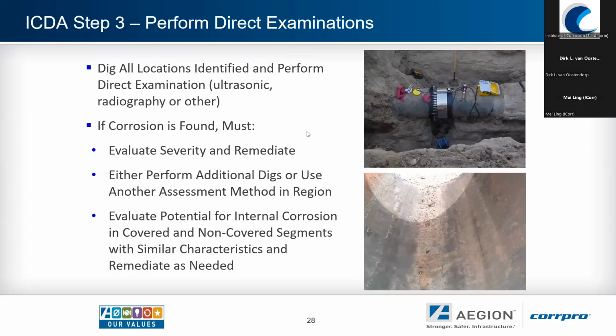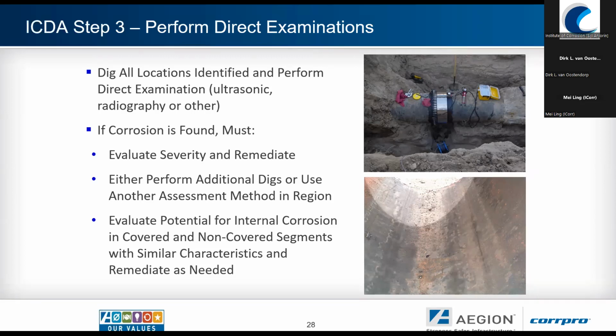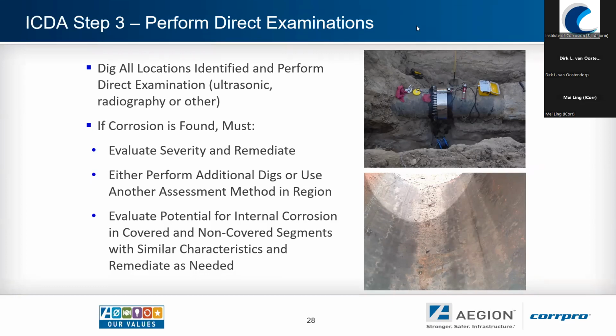The direct examination in the case of the internal corrosion is not quite the same as what we do for ECDA. Of course, it's on the internals. So typically we would end up using something like long-range guided wave ultrasonic as the first tool to assess for the internal corrosion and do the confirmation. If there are indications found and confirmed, this is where something like phased array or automated UT would be used to map it out further.